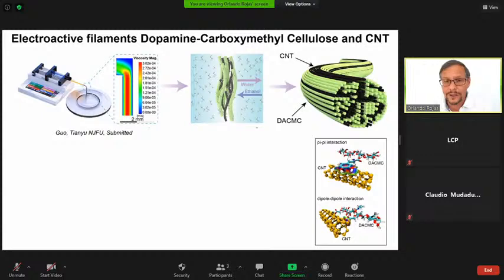It's very interesting to use nanocellulose as a dispersant of carbon nanotubes to produce conductive material. So that's well reported. But in this case, we chose to use carboxymethyl cellulose, which is very easy to couple with dopamine. And dopamine is quite interesting because then you can develop very strong water resistance. That combination of carboxymethyl cellulose and grafted dopamine, mixed with carbon nanotubes in water suspension, can be used as a dope for wet spinning. And here the amount of carbon nanotubes can be 10, 20%, 5%, so relatively small.